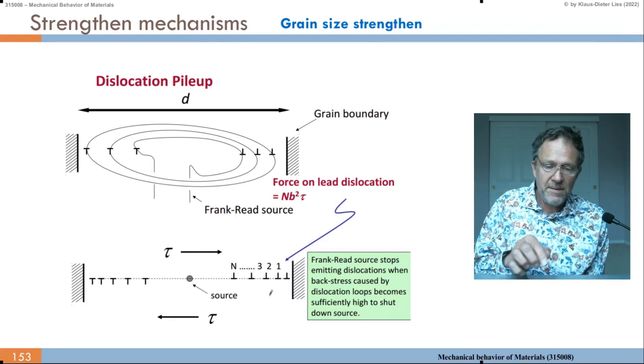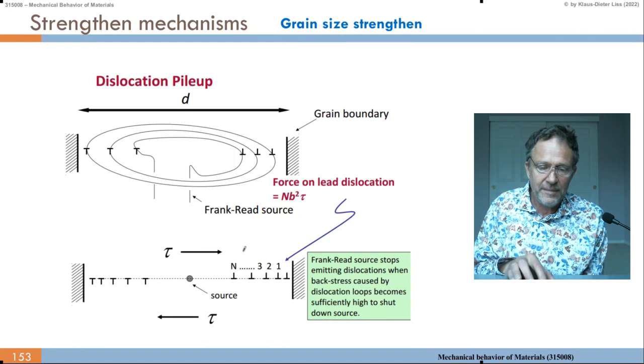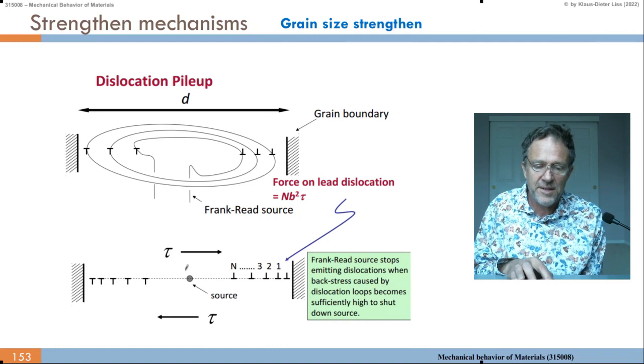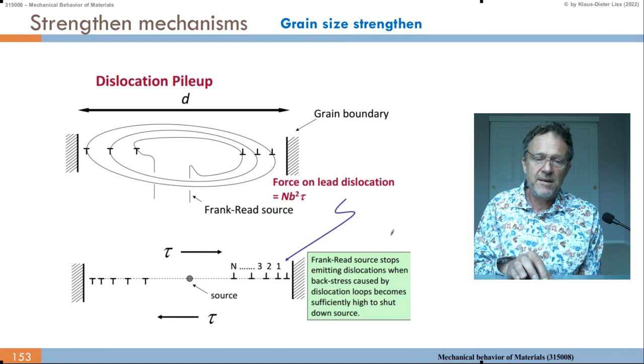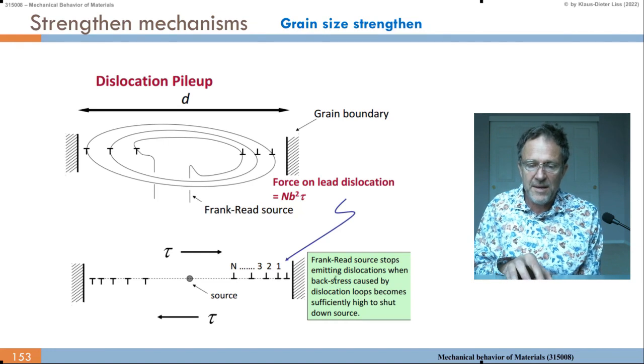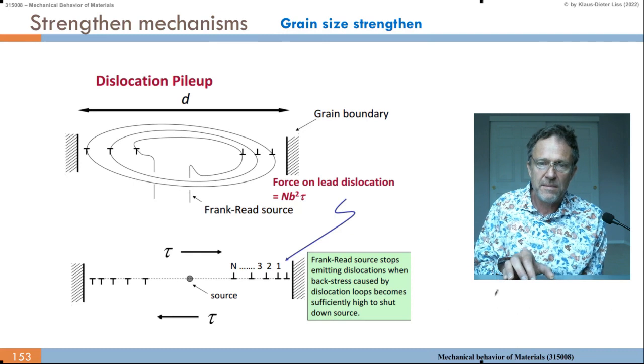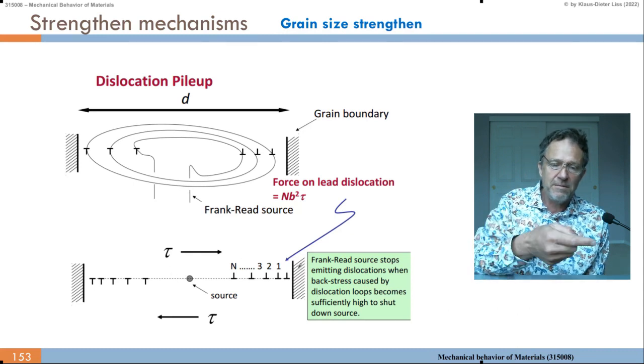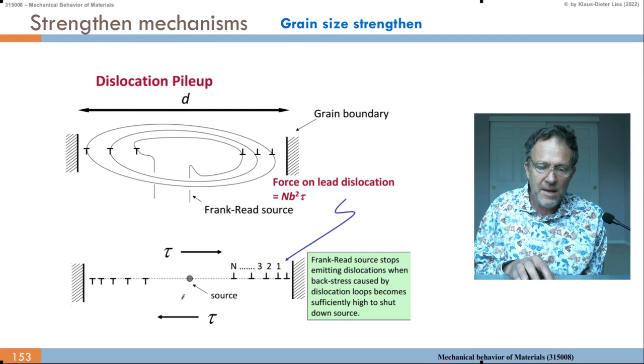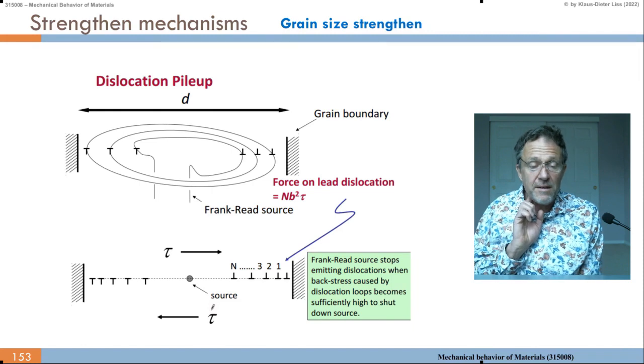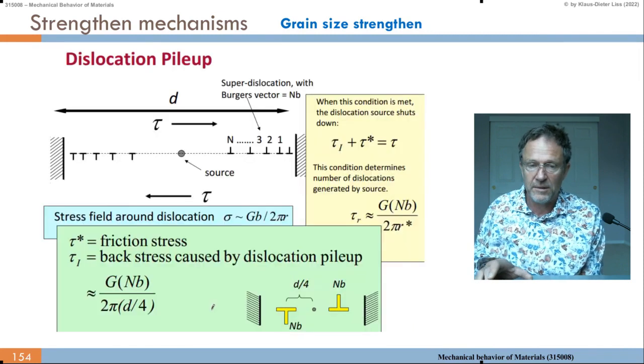So eventually that pile up gives a force, or it gives also back pressure. It gives a pressure or shear stress annihilating the externally applied shear stress, and that makes a Frank-Read source stop. So Frank-Read source stops emitting dislocations when the back stress caused by dislocation loops becomes sufficiently high to shut down the source. Yeah, dislocations cannot move to the right anymore, or on the other side to the left anymore. Then no new dislocations would be created in the Frank-Read source, and it would shut down.